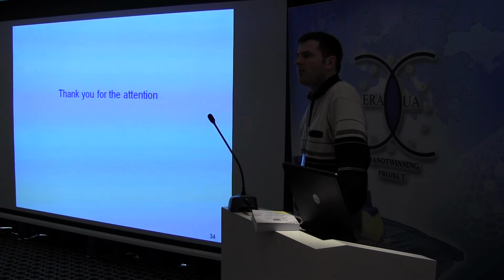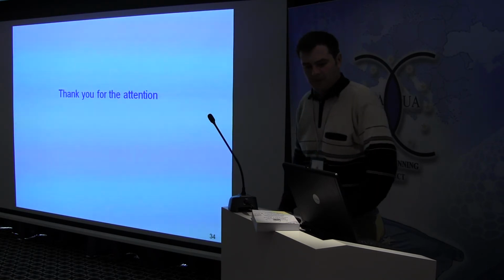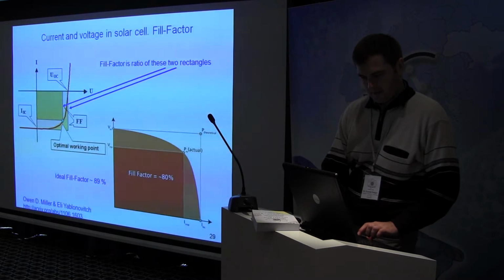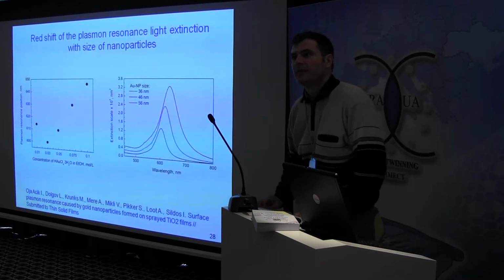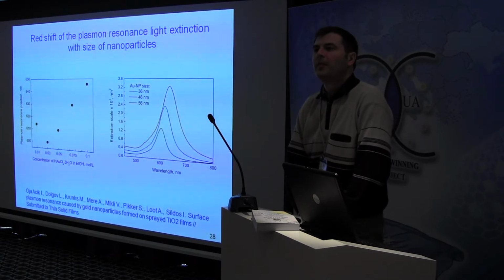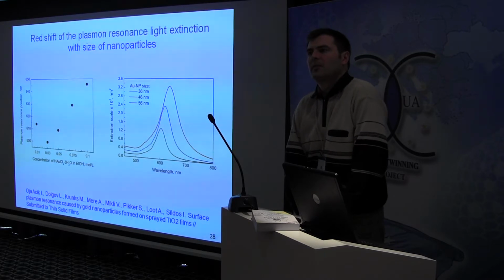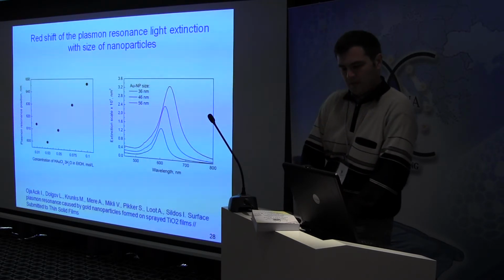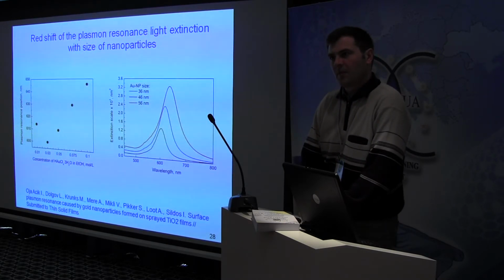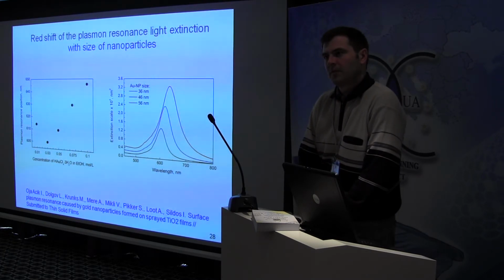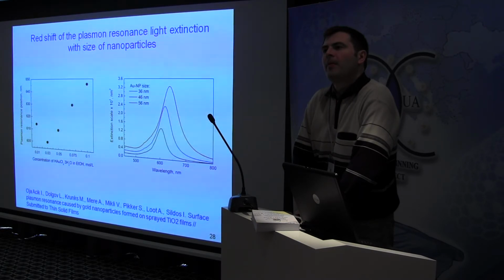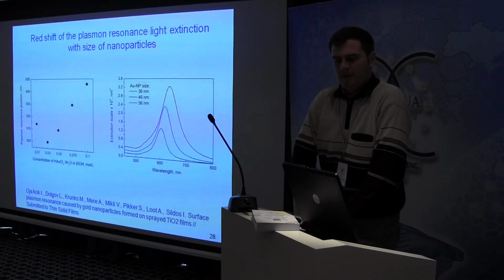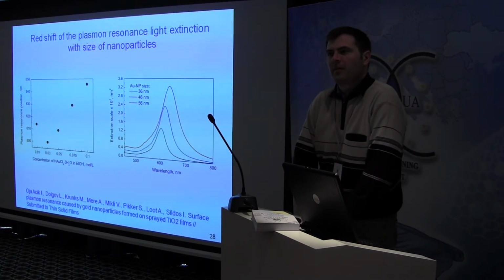Could you please show one of the last slides, when you showed the shift of the plasmonic band with the increase of the diameter? Right here, yes, the right one. Actually, as you show it, the shift seems to be relatively too big, a shift of about 50 nanometers in wavelength. For gold, it is known that an increase in the diameter from 30 to 50 doesn't give that kind of large shift. This resembles more an agglomeration of particles, because in the shifted spectrum you can see a shoulder at about 550 nanometers, and then a second band at about 650.